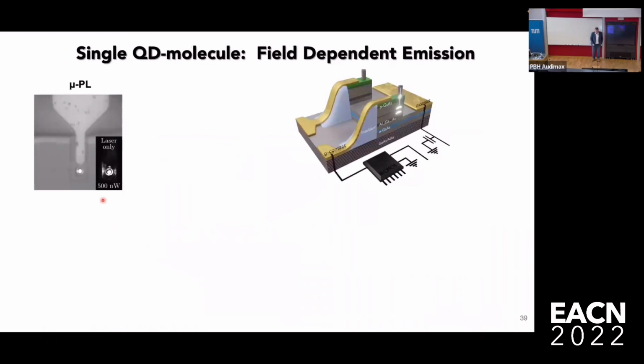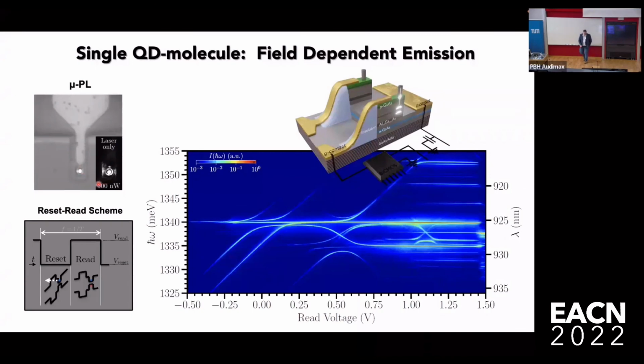And if you do then luminescence measurements on that, you can nicely see that single molecule lighting up at the end of that annular Bragg contact, and you can do spectroscopy on it. If you do spectroscopy on this thing, I can't describe in great detail, but that's what kind of thing you see. So you see all of these anti-crossings arising from this tunnel coupling that I told you about. You also see very, very complicated structures. And I want to kind of get out of jail by just showing you that actually we can find in here, by preparing the two charges, exactly the singlet triplet features that we were looking for to make the protocol.